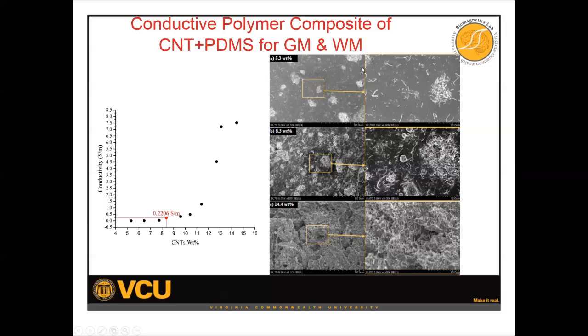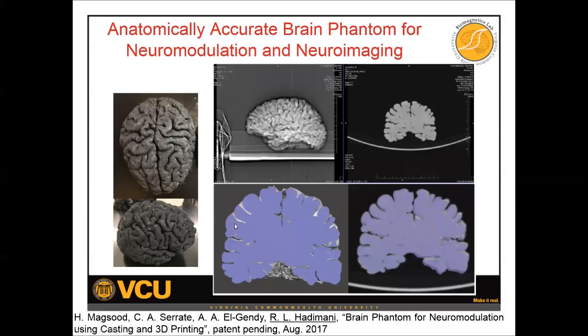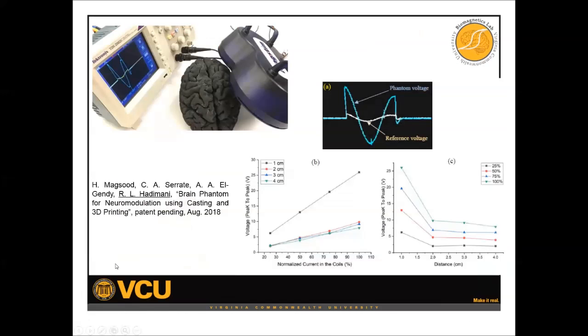So you can see in this graph, these are the scanning electron microscopic images with different carbon nanotube compositions. So in the graph, you can see that as you increase the carbon nanotube composition, the conductivity increases. So we had to use a composition that had similar conductivity as gray matter and white matter. So we also made sure that the phantom that was developed is anatomically accurate. We verified that using a CT scan of our prepared brain phantom. So the physical phantom that has been prepared is shown on the left-hand side. And then we measured the stimulation strengths using a TMS.